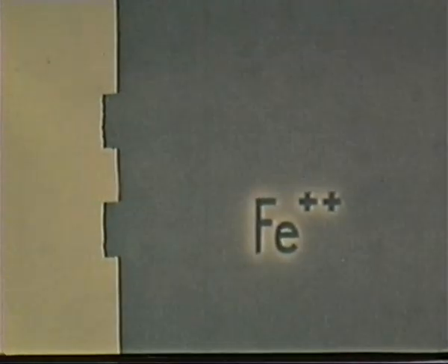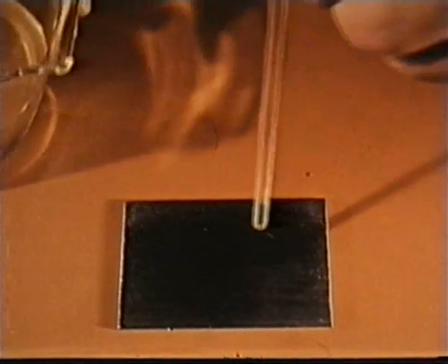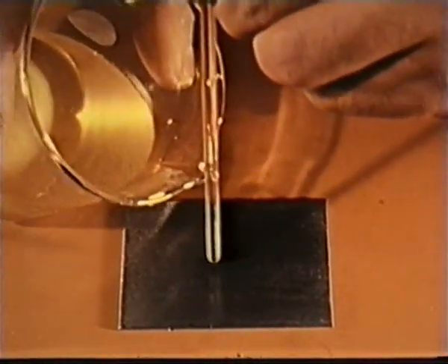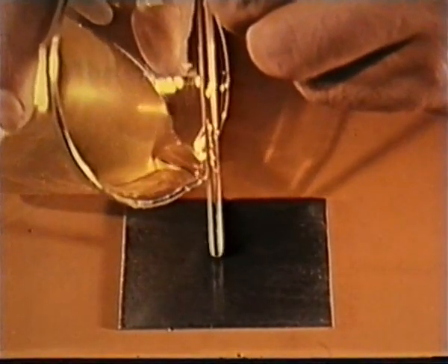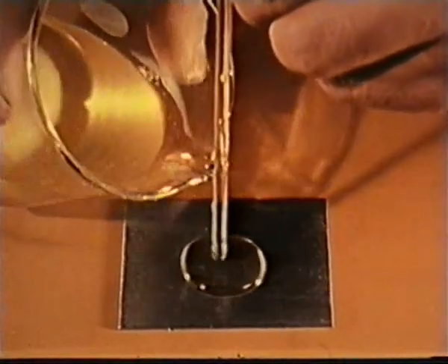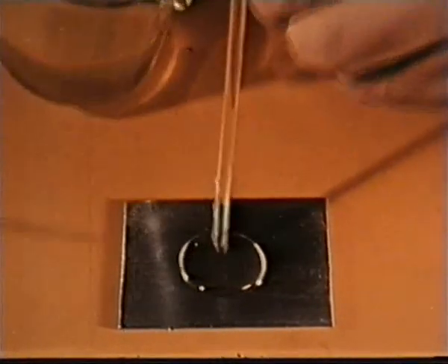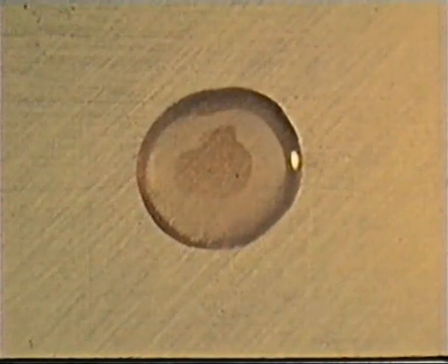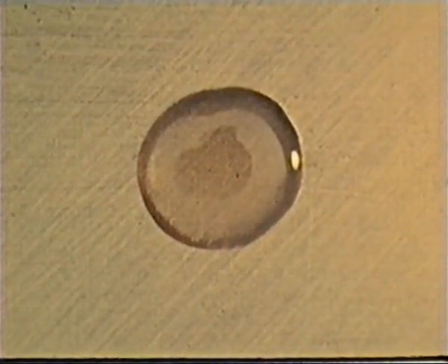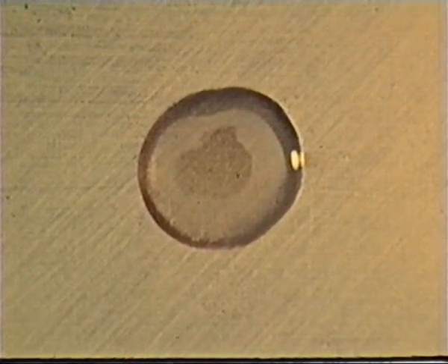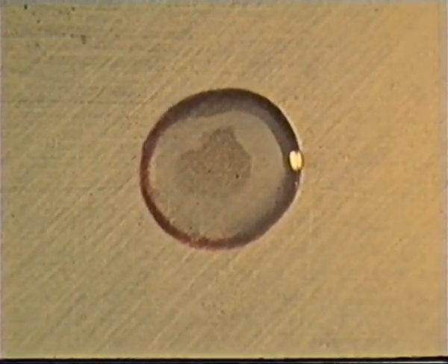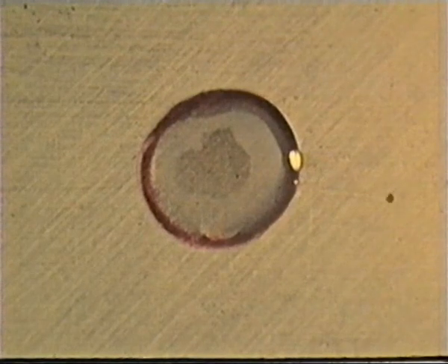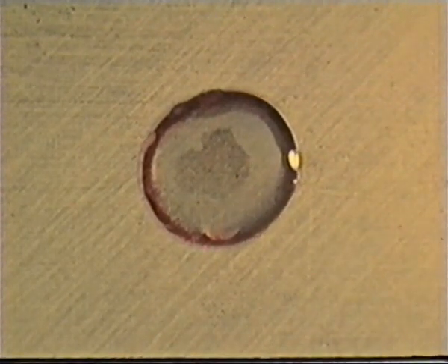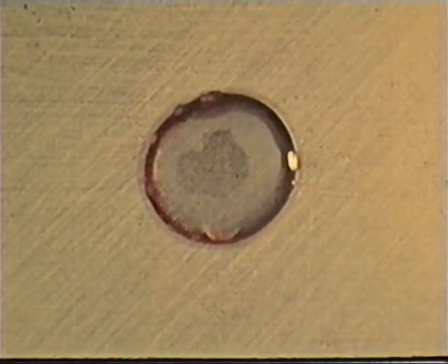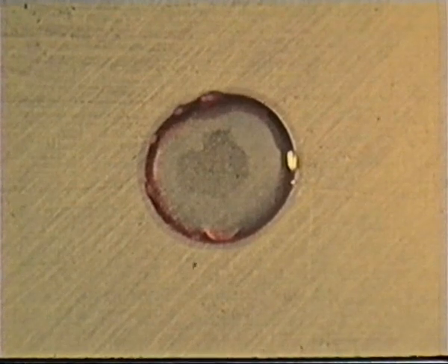Using these reagents, we can show the development and location of the anode and cathode in a cell established on an iron surface within a drop of gelatin containing these indicators. Oxygen from the air is more accessible to the periphery of the drop and sets up a cathode there as shown by pink color. Simultaneously, an anode, shown by the blue color, develops near the center of the drop, which is less accessible to oxygen.